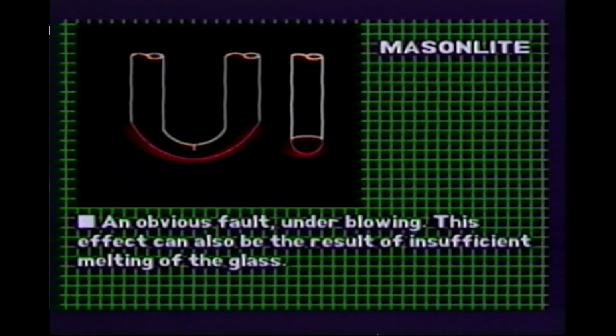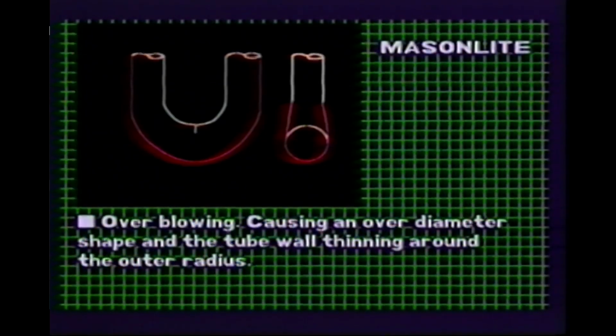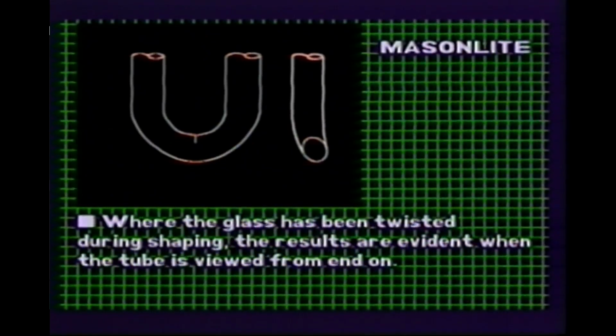An obvious fault, underblowing. This effect can also be the result of insufficient melting of the glass. Here, the opposite effect, overblowing, causing an over-diameter shape and the tube wall thinning around the outer radius. On this example, where the glass has been twisted during shaping, the results are evident when the tube is viewed from end on.